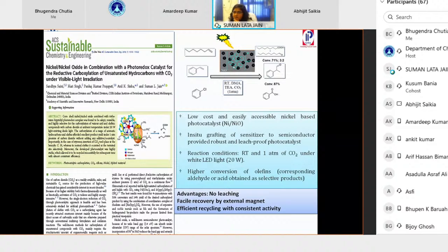Here we developed a heterogeneous system by combining both the components. So these are facile. We could easily recover the material after the reaction, and we could successfully reuse it for at least 3 or 4 runs. A number of olefins as well as aromatic compounds were successfully carboxylated, with only the formation of the carboxylated product. We did not get any hydrogenated products during these reactions. And one of the fascinating things is that the reactions occurred at room temperature as well as at 1 atmospheric pressure of CO2. So these are some advantages, and because nickel has a magnetic nature, we could easily recover the catalyst through an external magnet.